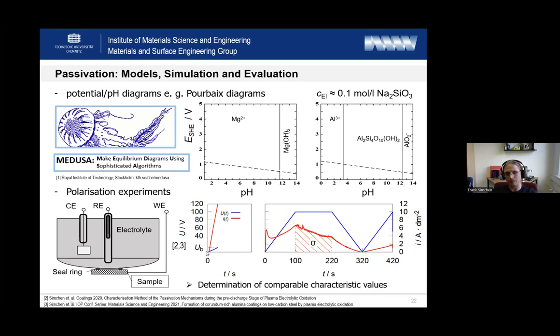So if the passivation is bad, we just achieve here this breakthrough voltage. If the passivation is better, we get a sigma value. And then step by step, if the passivation is getting better and better, the current flow is getting lower and the sigma value is getting lower also. So in one afternoon, depending how fast you are, you can test 10 electrolyte combinations in your setup. You just need a low amount of electrolyte and you can pre-select your electrolytes really fast.